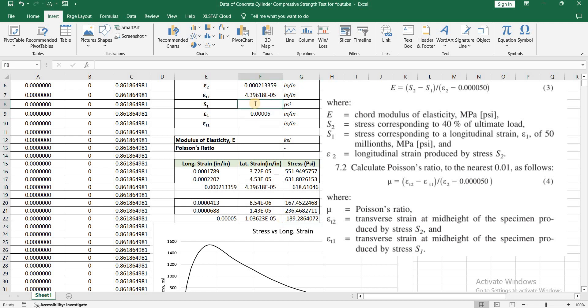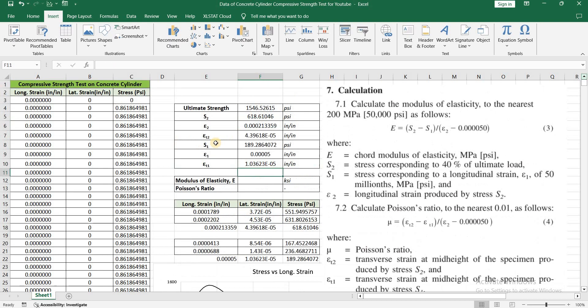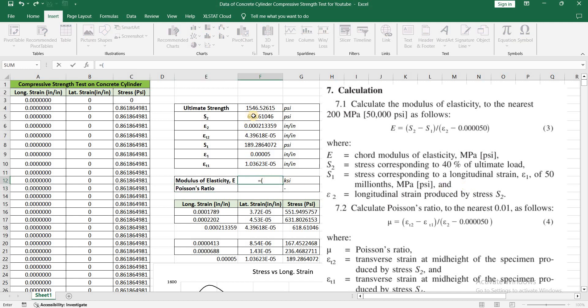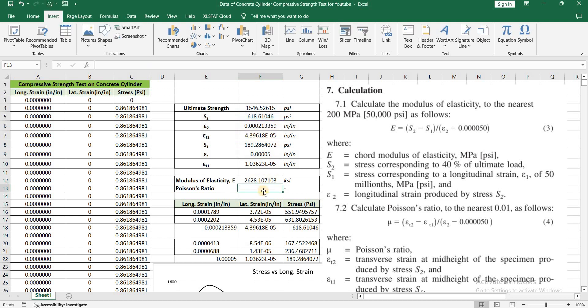In your main data table, put the value of stress S1 and the value of epsilon t1. Now your table is complete. You can find the modulus of elasticity and Poisson's ratio using the formulas given in ASTM C469. The formula for modulus of elasticity is (S2 minus S1) divided by (epsilon 2 minus epsilon 1), and I'm going to further divide by 1000 so that the modulus of elasticity value is in ksi.